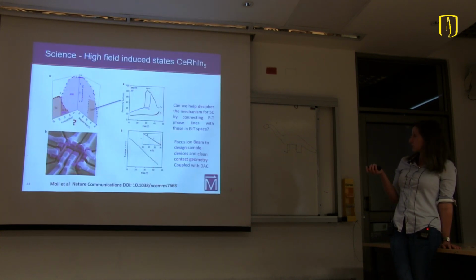So what kind of science can we do? If we look at this compound, cerium rhodium indium 5, it's a superconductor. If we look at this phase diagram, pressure versus temperature, it's an antiferromagnet with a superconducting pocket at high pressure. And if we look at zero pressure, but as a function of magnetic field, there is a nematic pocket or charge density wave that appears. But the big question is what happens in this region of the phase diagram, at low temperature, but pressure versus magnetic field. Basically, can we connect this superconducting pocket to this charge ordered phase?